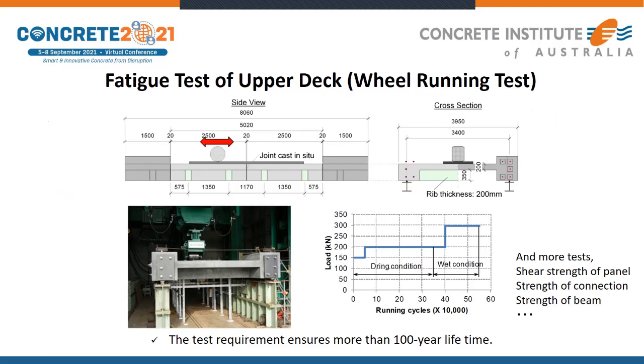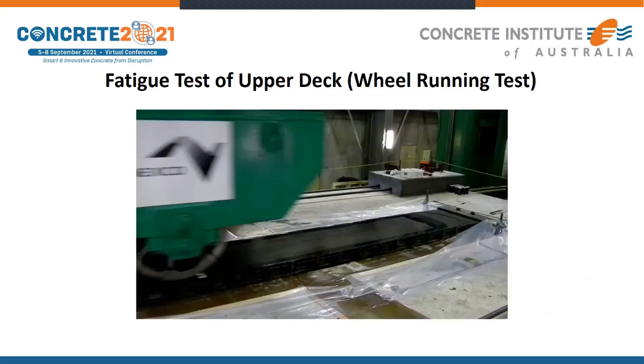We did many tests to confirm the behavior and to prepare the design manual. One of the tests is the fatigue test of the upper deck using a wheel running test. This is a requirement of the highway company to use a new technology on the highway. We increased the load up to 500,000 cycles. And after this test, we ensured more than 100 years lifetime of the new deck structure.